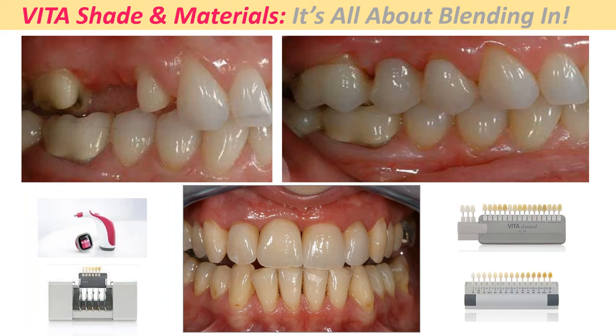And so no matter what shade system you use or material selection, eventually you'll get to the point where you can dial in and know, okay, on this particular case, I have this much material thickness. I'm going to use this material because it best fits for that indication. We're a company that doesn't necessarily like one material fits all. To us, it doesn't make sense. There are areas in which you need more cosmetic than you do strength. So you don't have to compromise aesthetics by getting something that's strong in a flexural strength test. You can have both worlds and make it work for that particular patient.